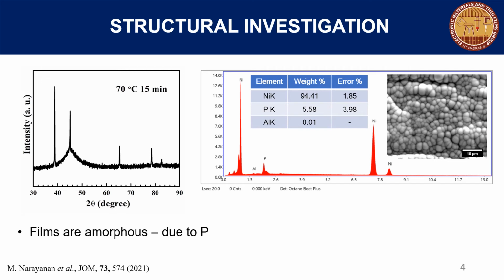The chemistry of the coating obtained largely depends upon the type of reducing agent used. Since the reducing agent used here is sodium hypophosphite, there is phosphorus co-deposition also occurring. Therefore, the coating we obtain is a nickel phosphorus coating. The XRD analysis of the coating shows a broad peak at approximately 45 degrees. This corresponds to nickel peak, and the broad peak indicates that the coating is amorphous in nature. This is due to the presence of phosphorus. The EDS data further confirms the presence of phosphorus.